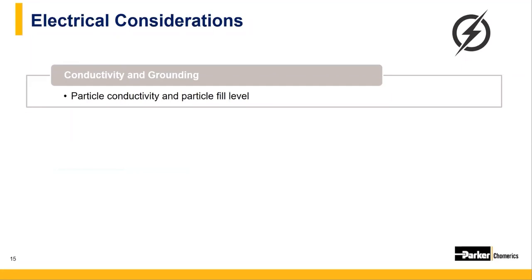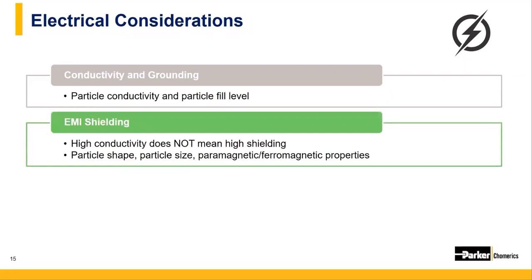Coatings need an even distribution of the fillers throughout the part to make sure the entire surface has the ideal properties. On a very important note, EMI shielding is not always directly correlated with particle conductivity. Let me emphasize this. High conductivity particles will provide good EMI shielding, but low conductivity particles can also provide very good EMI shielding because of factors such as particle shape, particle size, and paramagnetic or ferromagnetic properties. These properties will actually impact the shielding at lower ends of the frequency spectrum, specifically in the magnetic field range.